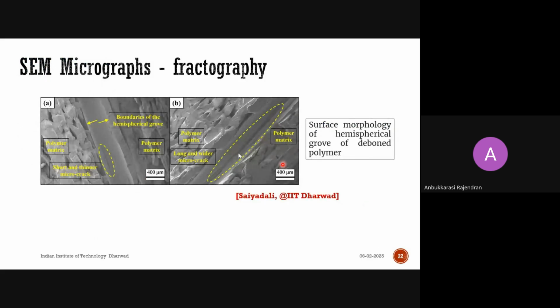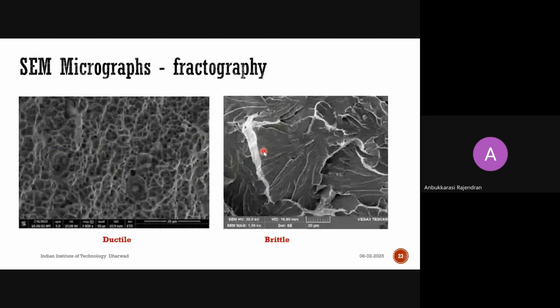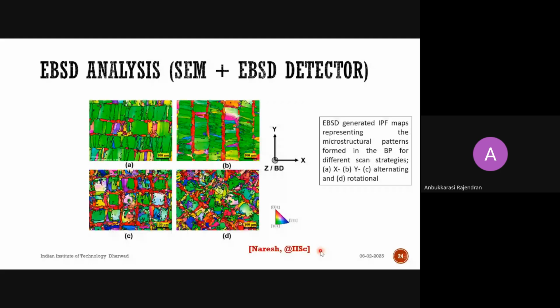Again, SEM can be used for doing fractography. This is one of the polymer samples; the fractured surface under SEM shows the fracture propagation, right? If I am doing it for metallic samples, as we are familiar, they can show ductile fracture and brittle fracture. The ductile mode of fracture can be understood from the way of fracturing: it is the presence of dimples in the fractured surface. The presence of a flat surface shows the brittle fracture.